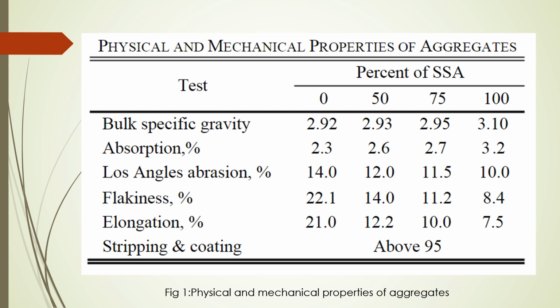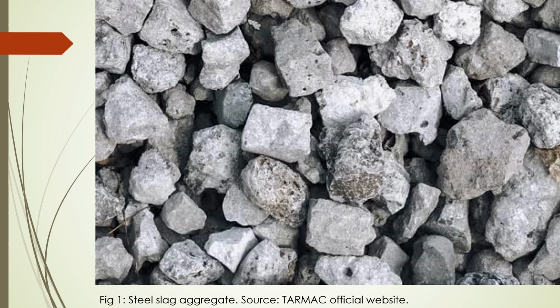Next test is elongation percentage. Its value is 21.0 when the percentage of steel slag aggregate is 0%, and it decreases up to 7.5 when the percentage of steel slag aggregate is 100%, and it should always be less than 15%. It is the same as flakiness percentage. Next one is stripping and coating. It is above 95. Here is the picture of steel slag aggregate, and we see that it has a vesicular structure.